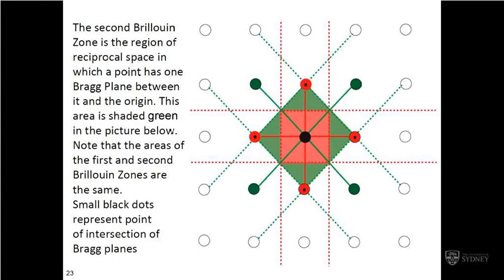The second one is the green area, and it's very much like we did with the Wigner-Seitz cell last lecture. To get the green one, you start at the origin, you go out to the next nearest lattice point. Next furthest away are the green ones. You put a line bisecting point to point, and then another perpendicular line over here, another one here, and so on. And then you generate that green shape. Is that clear? I think it's clear. You let me know if it's not clear.